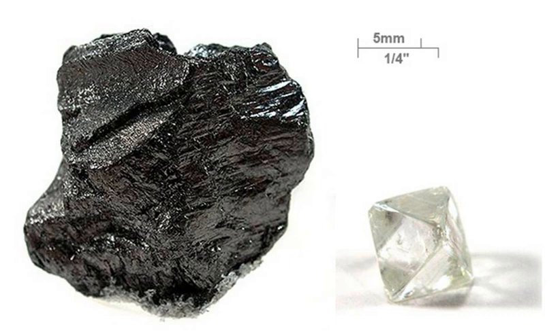Carbon generally has low toxicity to life on Earth, but carbon nanoparticles are deadly to Drosophila. Carbon may burn vigorously and brightly in the presence of air at high temperatures. Large accumulations of coal, which have remained inert for hundreds of millions of years in the absence of oxygen, may spontaneously combust when exposed to air in coal mine waste tips, ship cargo holds and coal bunkers, and storage dumps. In nuclear applications where graphite is used as a neutron moderator, accumulation of Wigner energy followed by a sudden, spontaneous release may occur. Annealing to at least 250 degrees Celsius can release the energy safely, although in the Windscale fire the procedure went wrong, causing other reactor materials to combust.